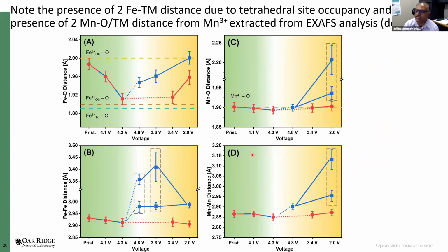So this is just to wrap things up, and just for our visual pleasure, I just want to show that in the manganese-oxygen, as expected at 2 volts, there is a splitting of this manganese-oxygen bond distance, as well as a splitting of this manganese-transition metal distance. Both of these are consistent with the presence of Jahn-Teller manganese. If you look at 4.8 volts and 3.6 volts, the iron distance is now split. The presence of the split distance is again consistent with the iron occupying tetrahedral sites in addition to octahedral sites at these voltages.